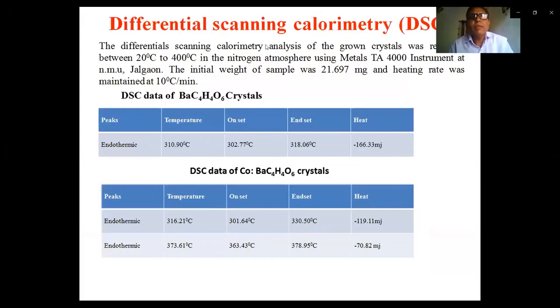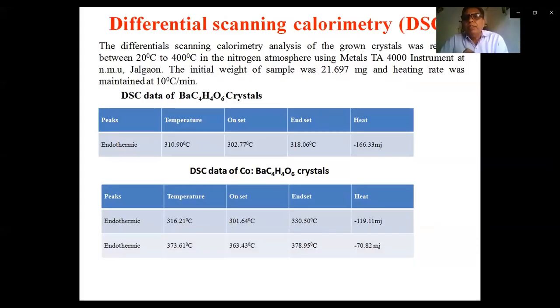Differential scanning calorimetry, DSC. In this case, the initial weight of the sample was 21.697 mg, and the heat rate was maintained at 10 degrees Celsius per minute. In the DSC of the barium tartarate crystal, one peak was observed, with the first temperature around 310.90 degrees Celsius, onset 302 degrees Celsius, and end set 318.06, and heat loss of -166.33 mj.